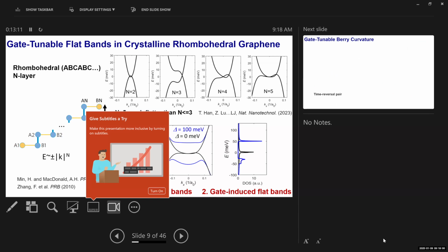Well, what really matters for us is that when you open up the band gap, you're further squeezing the bottom of the conduction band. You make it more flat and enhance the density of states even more compared to what I call pristine flat band that's degenerate at zero energy without gating, okay?